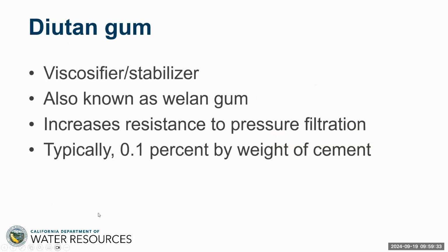Next slide. Diutan gum. Now this is excellent. A more recent discovery in our grouting business. Diutan gum, also known as welan gum, is one of the components of, what do you call it? A foodstuff. It's gone completely out of my head because I don't eat it. But it causes stability in the foodstuff. And basically, instead of your container of, say, cream cheese or something like that, just being very fluid, it gives it body. So in our grouts, what we like about the gum is that it gives resistance to pressure filtration. I remember how important that was from earlier on. So basically, it helps to bind the water into the system. The material I was thinking about was yogurt. You check the label on a container of yogurt, and you'll probably find gum is added. Very small amounts, typically 0.1% by weight of cement, so you don't need a lot on site. Very easy to handle. It can either be fluid or it can be powder.